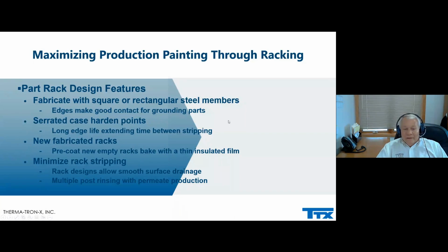New racks should be pre-coated with a thin insulated film. Now that's great for e-coating, right? What about powder? Everybody wants to go powder. Think about it. How much powder gets applied to the traction of a rack that has just been freshly stripped? Now, one of the things that you could do is pre-coat those through electrocoat or a supplier with electrocoat, or you pre-coat that with a very thin powder and bake those racks out, and having that edge with a square edge, having that area with a grounding gives you the ability to retain that ground in a very thin coat, and minimizes the amount of powder being applied on the rack, because what you end up with is an insulating quality.